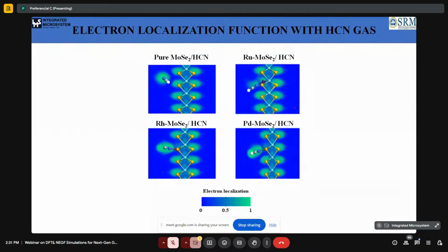Right. So based on all those things, we have taken a pristine MoSe₂ monolayer and functionalized it with a set of transition metals by means of a substitutional doping process. After the functionalization, we did the gas adsorption analysis by calculating the adsorption energy and by studying the charge transfer as well as electron localization function analysis. With respect to all gases except hydrogen, the other two gases are well adsorbed by the doped system when compared to the pristine MoSe₂ monolayer.